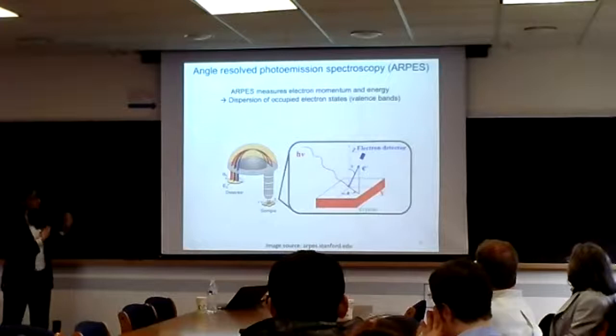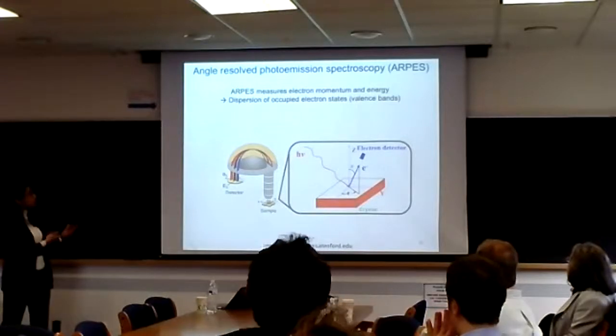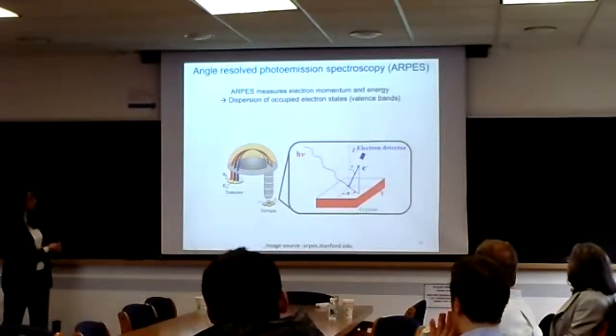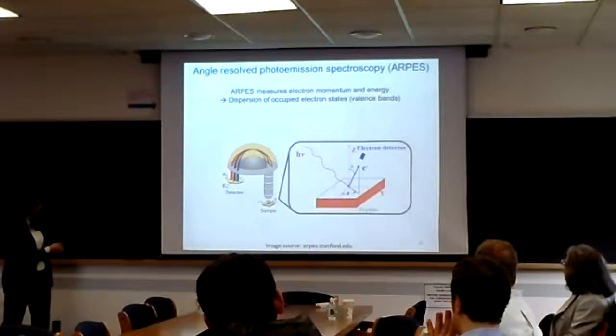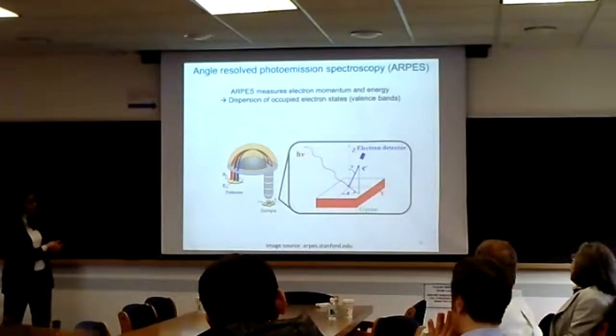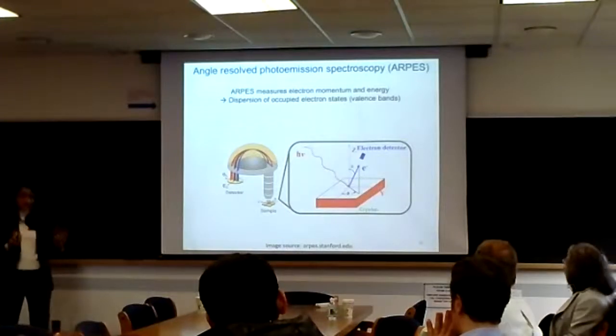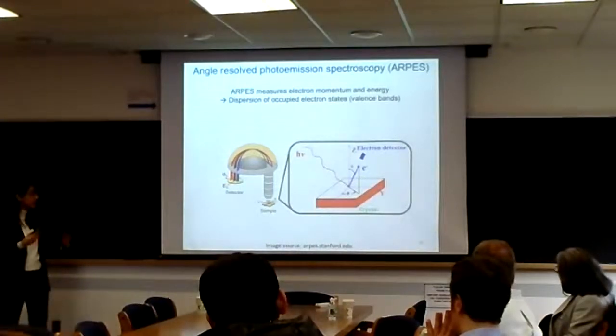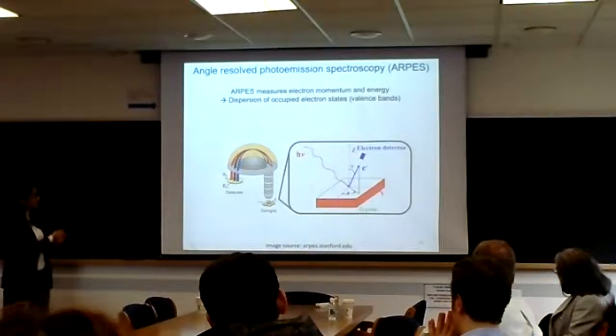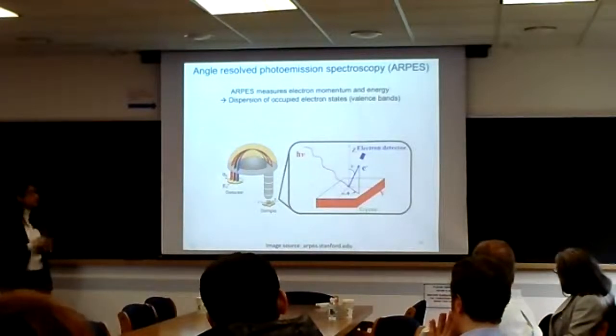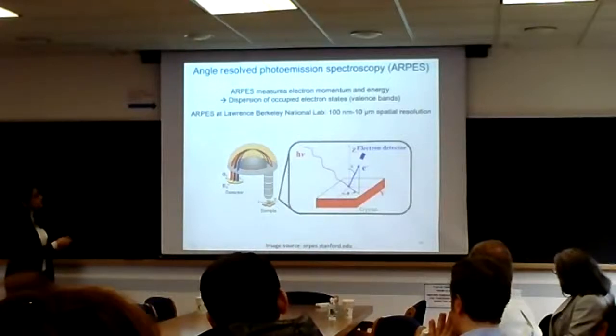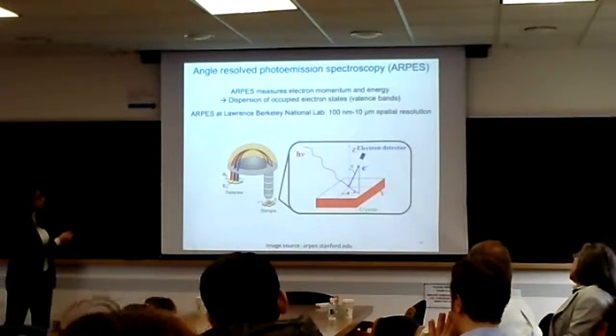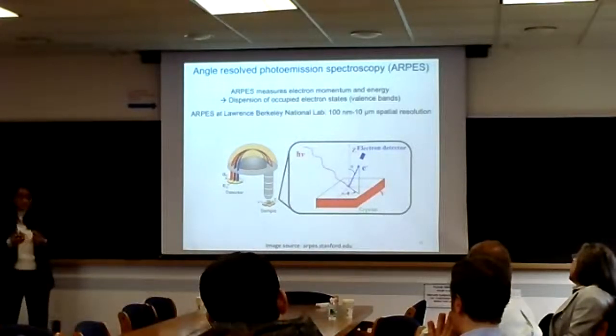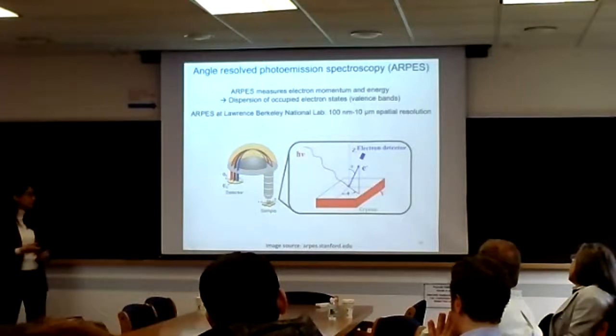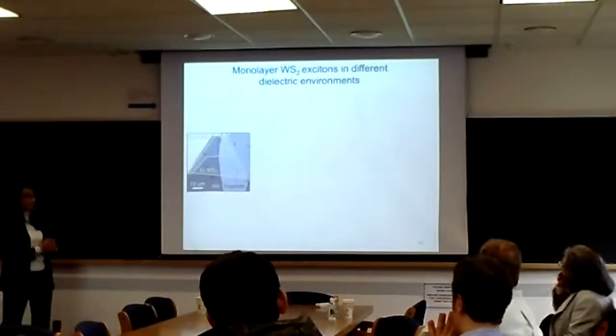In this measurement, we are striking our sample with high energy X-rays, and then measuring the electrons that are knocked out of the sample. They have enough energy and momentum, and you detect them in a hemispherical detector, which gives you this information. And again, the neat thing here is that they can actually vary the spot size to do correlated optics with ARPES here.